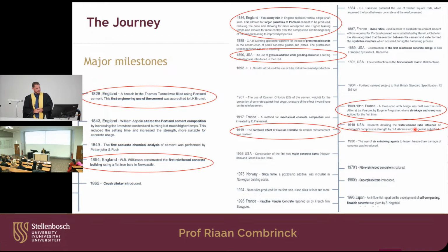Then another one was calcium chloride. They saw that calcium chloride attacks the reinforcing steel. And I think this is an important one because it sort of set the stage for durability issues in concrete. They saw the chlorides attack the steel and the steel starts corroding and you can't use the structure anymore. But it's also oxygen and water and all of those things that you need for corrosion. And this is a very important step that we found that it's not just designing concrete, but designing concrete that actually lasts.